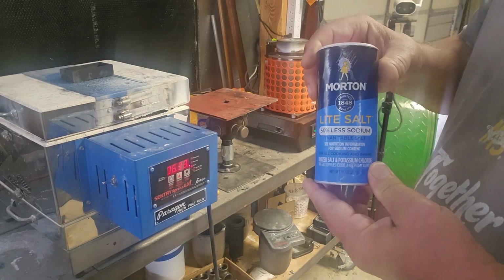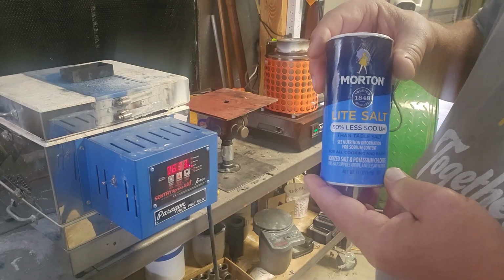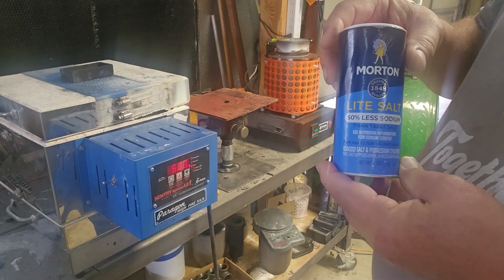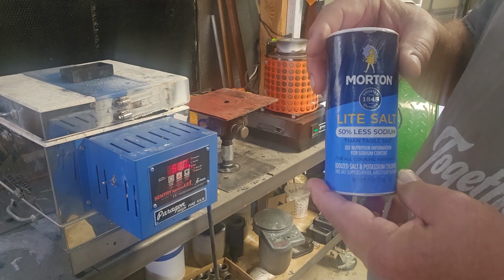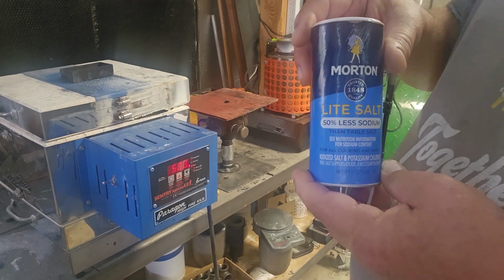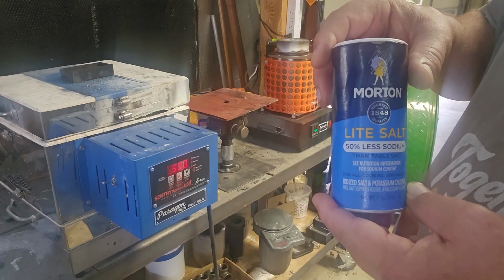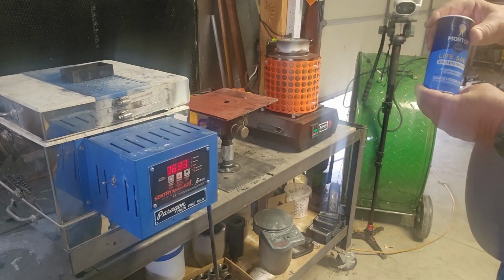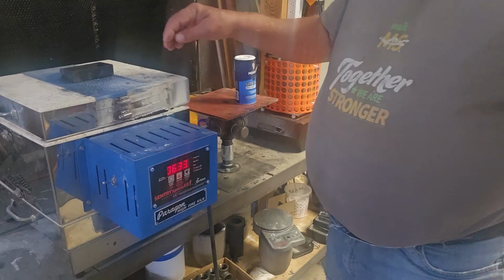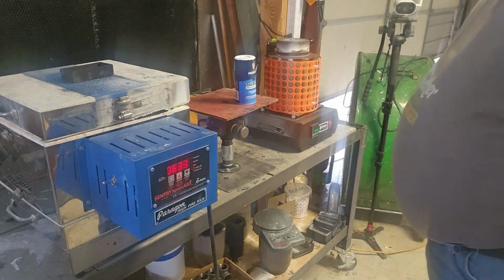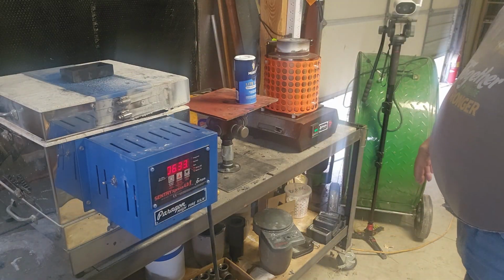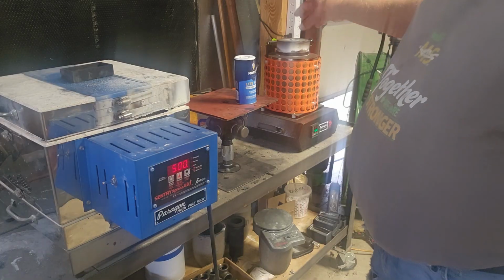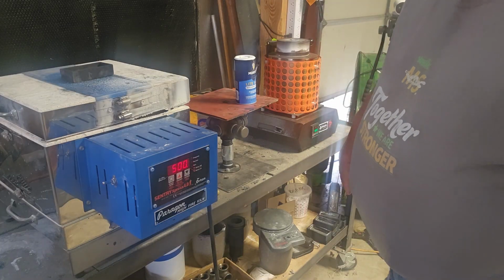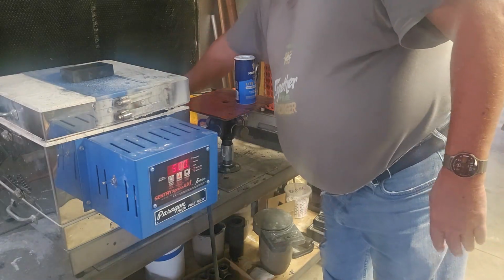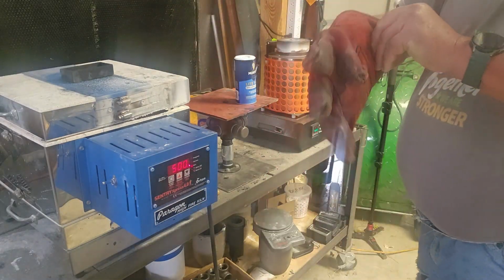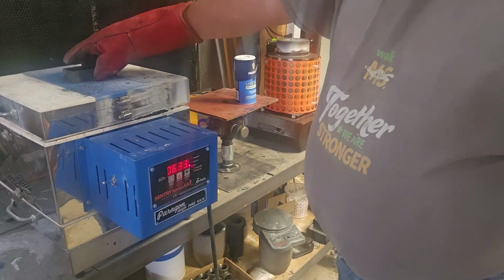I forgot to mention that I put a little bit of this light salt in there for flux. This is half sodium chloride and half potassium chloride, and it helps separate the clean metal from the oxides and all that stuff. I'm preheating this little ingot mold just to make sure that there's no moisture in there. In case I have more aluminum than I can use, I can pour it in there, but I won't need it, but I do that anyway. Gloves are very important on this because everything is very, very hot.